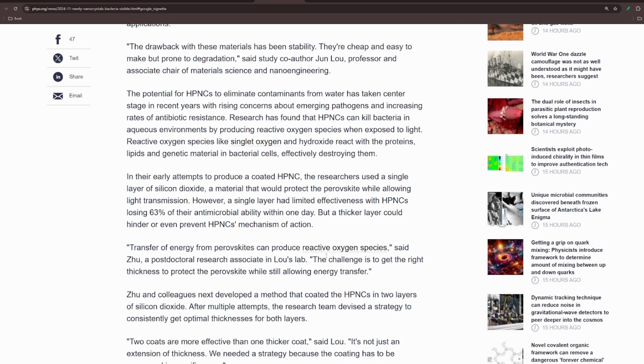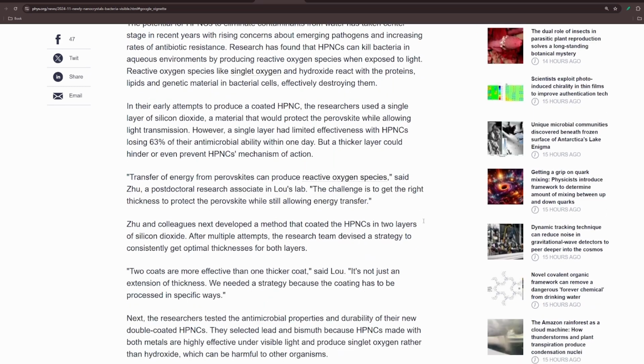destroying them. In their early attempts to produce a coated HPNC, the researchers used a single layer of silicon dioxide, a material that would protect the perovskite while allowing light transmission. However, a single layer had limited effectiveness with HPNCs, losing 63% of antimicrobial ability within 1 day. But a thicker layer could hinder or prevent HPNC's mechanism of action.